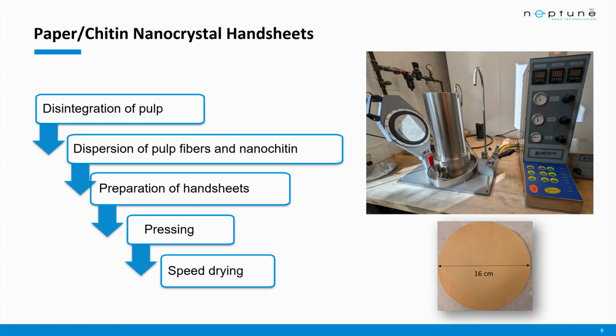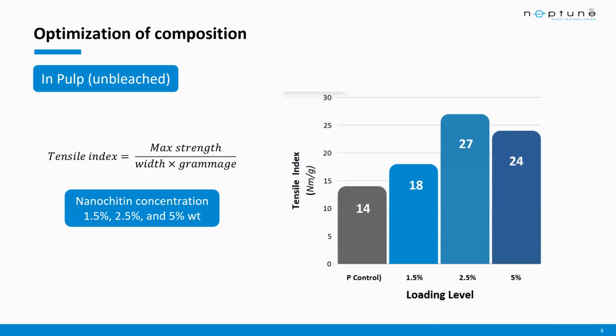And here are some of the tensile strength results. Here it's normalized by grammage. And the gray bar that you can see here is really the control specimen, which is a grade of unbleached softwood paper pulp without any modification. And then the different shades of blue are specimens containing various loading levels of chitin nanocrystal, anywhere between 1.5 to 5%.